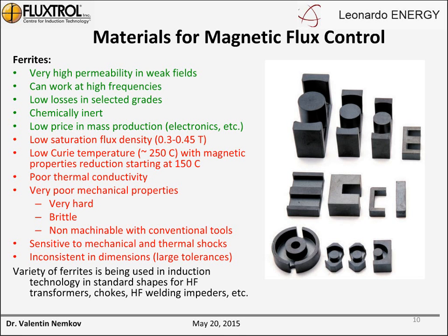The drawbacks: a low saturation flux density, it's 0.3, 0.45 Tesla, which limits the application, especially for low frequency applications. It has a relatively low Curie point, which is 250, sometimes a little bit higher, but magnetic properties start to deteriorate at about 150 C. Ferrites have relatively poor thermal conductivity, and what's very, very important, very poor mechanical properties. They're very hard, they're brittle, they're non-machinable with conventional tools. They are sensitive to mechanical and thermal shocks.